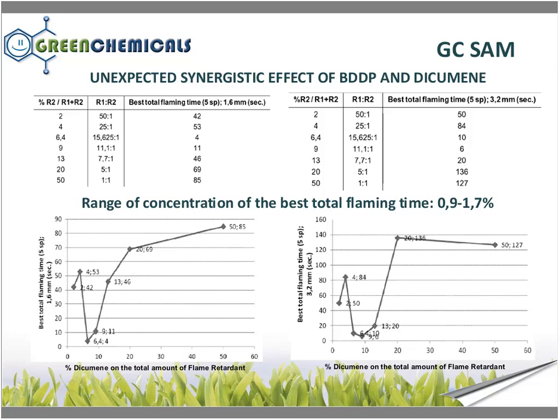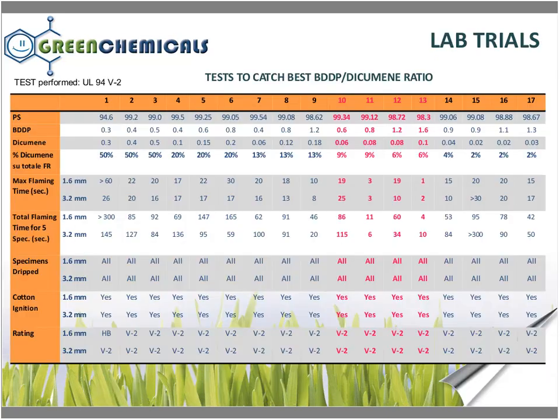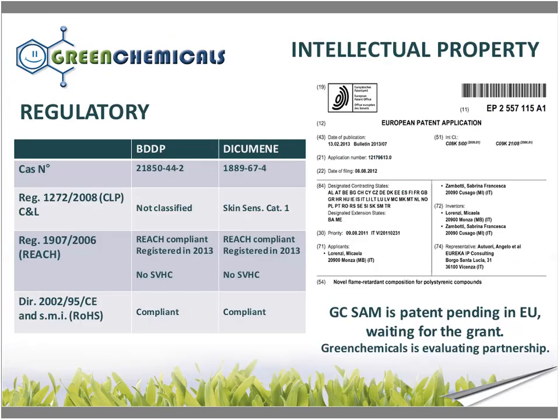In particular, you can see here that when we work with a percentage of dicumene between 6 and 9% of the total amount of the flame retardant, we have the best extinguishing times, with only a total amount of flame retardant between 0.9 and 1.7%. This is just to show you all the tests that they've done to arrive at this ratio and to develop our solution.